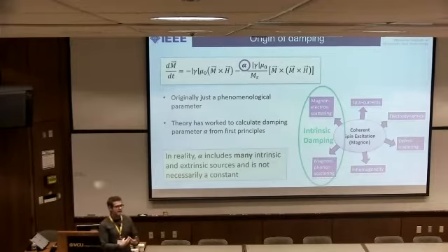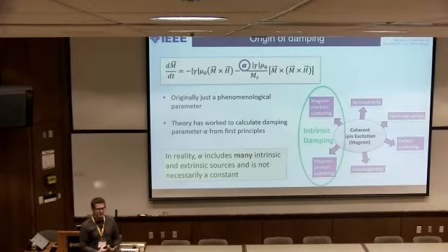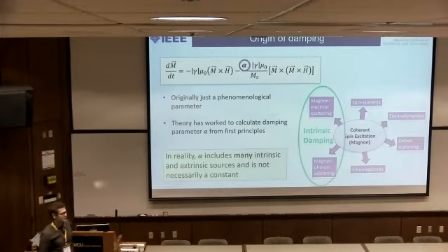But this is a terribly, terribly inefficient process. That's why insulators such as YIG or ferrites have very, very low values of damping. They don't have conduction electrons, they don't have this sort of scattering process, and this is very, very inefficient.